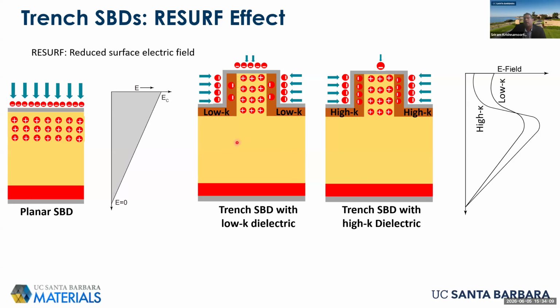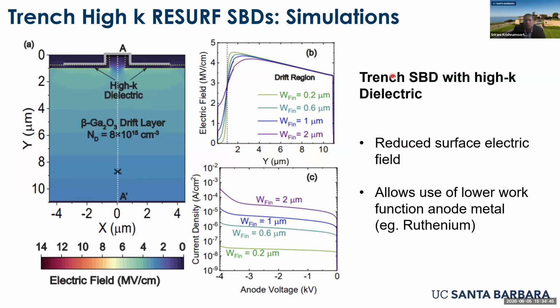And so in my group, we took this idea and modified it to include high K dielectrics. And if we had high K dielectrics, we can further reduce the surface electric field compared to a low K dielectric. And what that helps us is that now you can start using a low work function metal, and you can make a Schottky diode with a low turn-on voltage while still preserving the reverse leakage because you're reducing the surface electric field. So it removes or modifies the trade-off between the on-state and off-state for a Schottky diode.